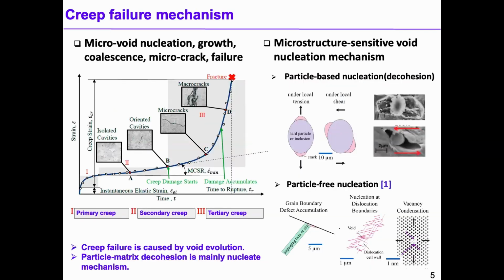So in our research, creep failure is caused by void evolution at high stress range and high temperature. The void nucleation can be divided into 2 parts: particle-based nucleation and particle-free nucleation. At high stress levels, particle-matrix decohesion is the main nucleation mechanism, and at low stress range, void nucleation will happen at grain boundaries, at dislocation boundaries, and in the grain.